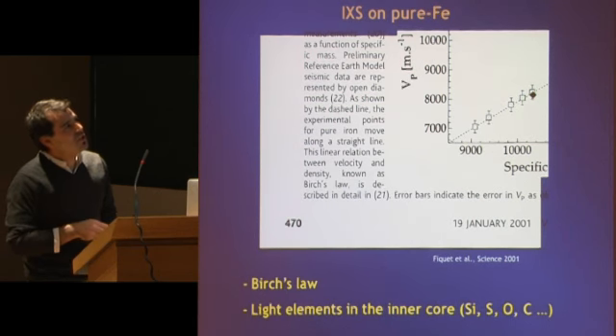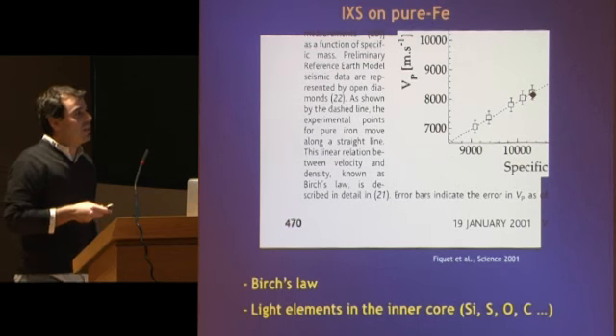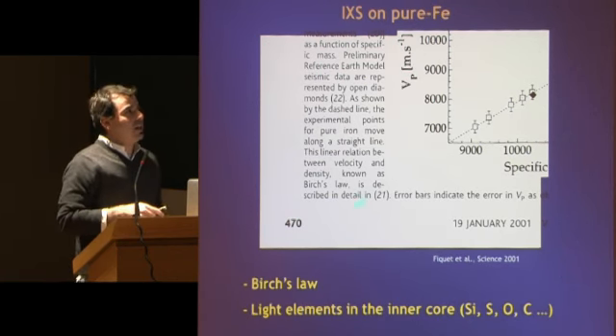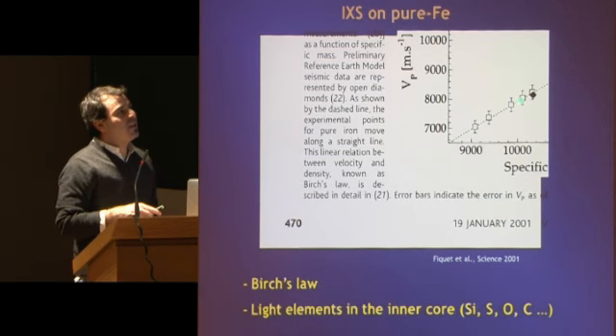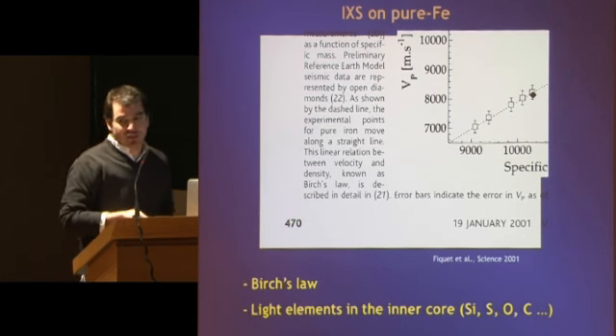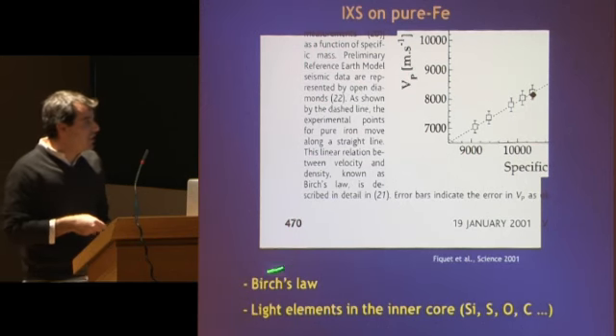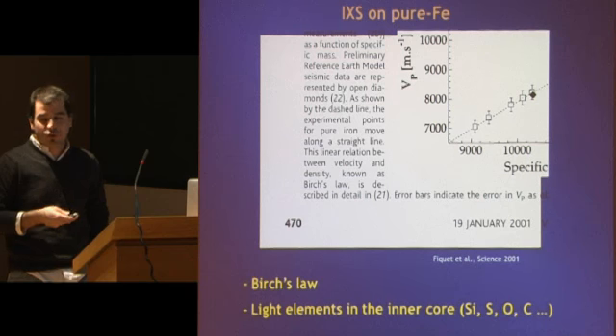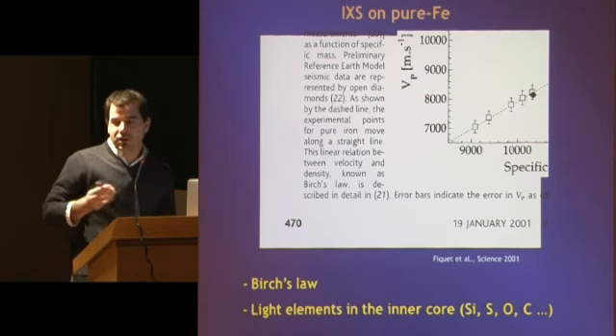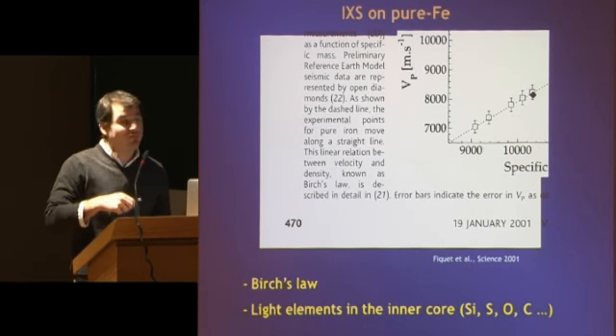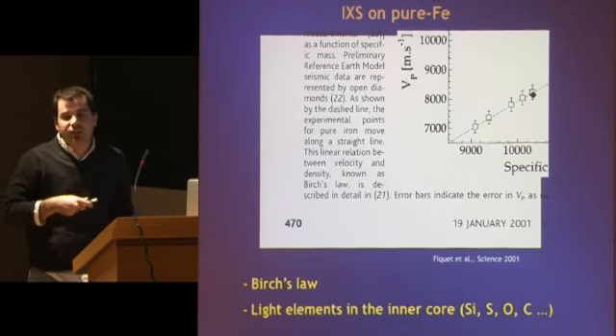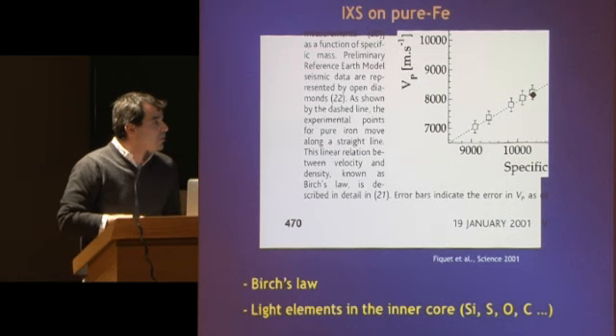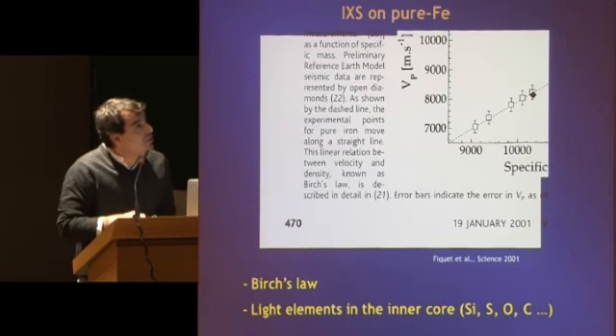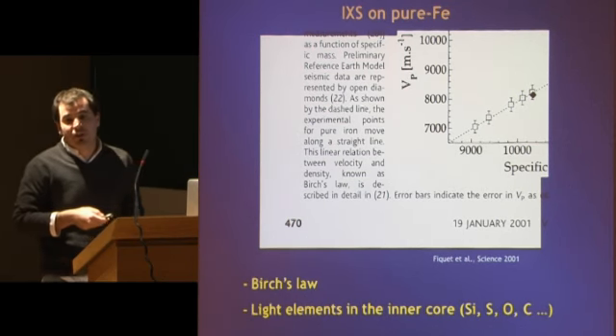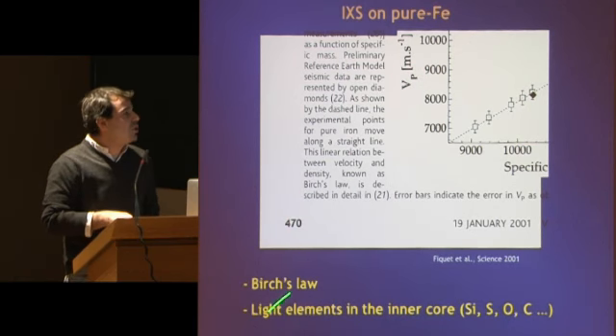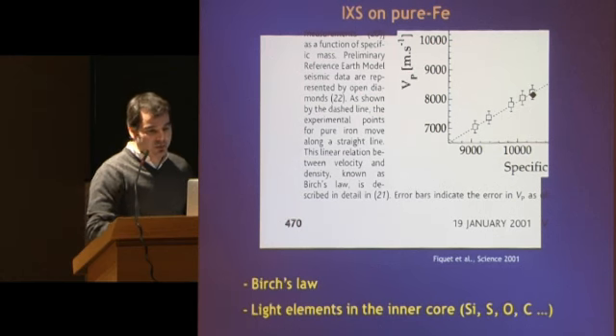You can just see one of the shock wave measurements. Here the idea is to say that the measurement performed under static pressure compares well with the dynamic data, and they all plot on a line when plotted as a function of density. This on one side supports the validity, at least as a first order approximation, of the Birch law, so a linear dependence of the compressional velocity on density or volume irrespective of the specific pressure and temperature condition. That is something that can be understood in the framework of a quasi-harmonic approximation. Furthermore, this extrapolation, and this is the part that unfortunately you cannot see, extrapolates lower than the velocity of PREM. So that again brings an argument in favor of the presence of elements lighter than iron.